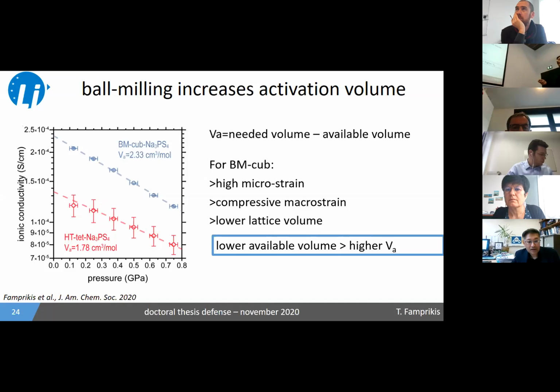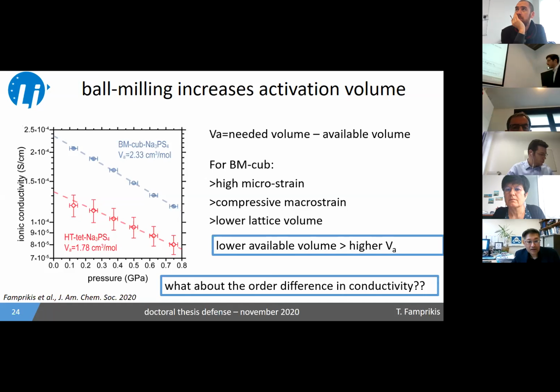If you look carefully, however, on the scale on this graph, you will see that both samples actually conduct very closely to each other in terms of the value of the conductivity. They're both in 10 to the minus 4 Siemens per centimeter, which is a bit in contrast to what I was talking about before, about an order of magnitude difference between them. So was I lying? Not really.